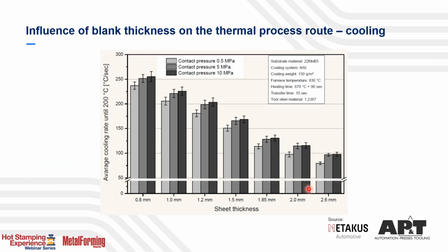Last but not least, the influence of the contact pressure related to the average cooling rate until 200 degrees in kelvins per second or degrees per second here. We have different sheet thicknesses here on this axis, and then we have the different contact pressures that are applied inside the tool, and we have been varying them from 0.5 megapascal up to 10 megapascal, and what you can immediately see is that the influence is actually not the biggest. So the difference between the different quenching rates is not the highest, and what I want to pinpoint here is that a lot of customers, a lot of stampers out there, we're selling, for example, press hardening presses from 1200 ton up to 1600 tons, and what we see out on the market is that most of the stampers are applying always maximum force, but this is actually not needed. This is causing a lot of energy consumption.